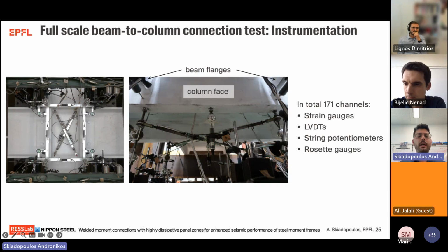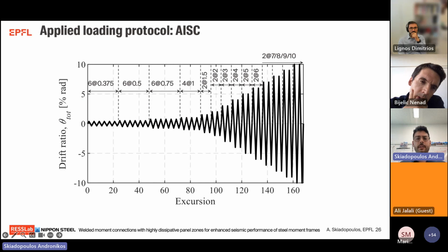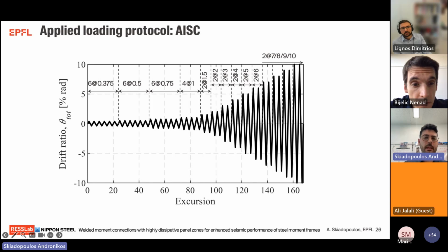To measure the experimental variables of interest, an instrumentation plan that includes 171 channels was employed, and this included strain gauges, linear variable differential transducers, string potentiometers, and rosette gauges. Due to time brevity, I will show the experimental results of only one specimen that was subjected to the standard symmetric cyclic loading protocol of the American and also the European provisions. And this loading protocol was applied so that the connection performance is assessed comparatively to the American and the European pre-qualification criteria.